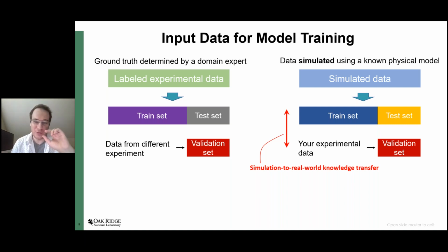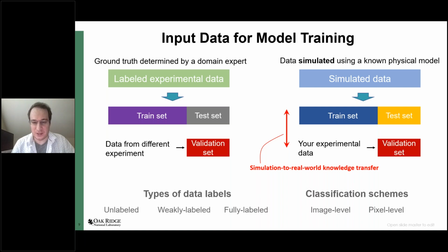And then the interesting thing is what I call simulation to real world transfer, because we train our model on the simulated data, but then we actually apply it to real experimental data. And this can be very tricky sometimes, because in some cases we can have nearly perfect accuracy achieved on the simulated data, but then we apply it to experimental data, and it turns out that it doesn't work. And it turns out this is because we didn't take into account certain forms of noise or certain forms of distortions that are common in the experiment. So it usually takes a lot of time to figure out how to prepare a proper training set.